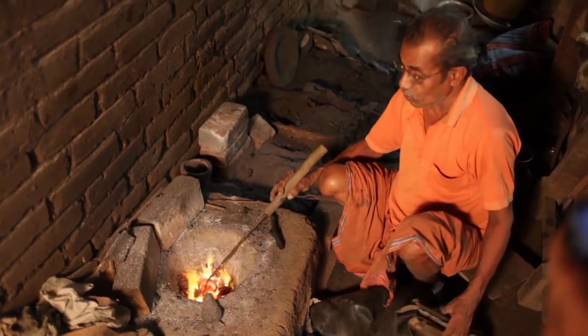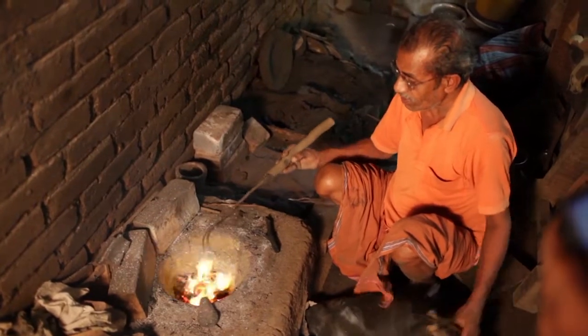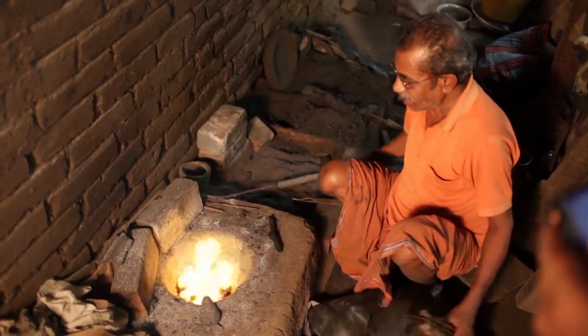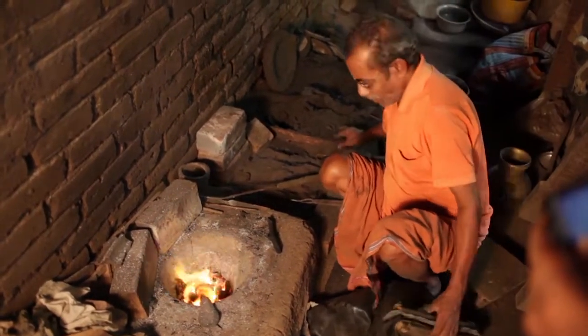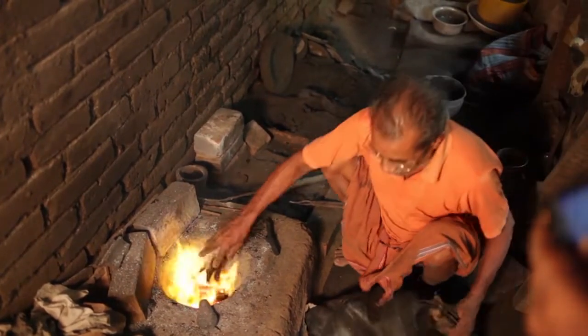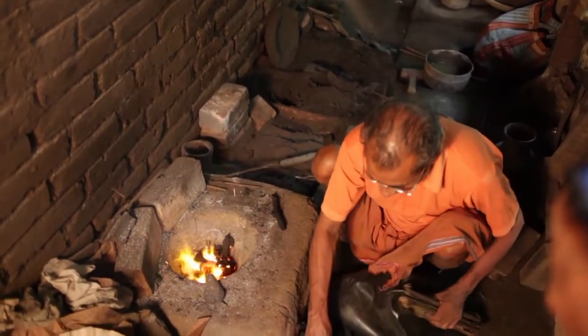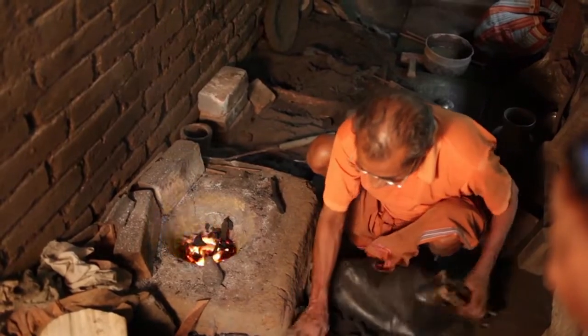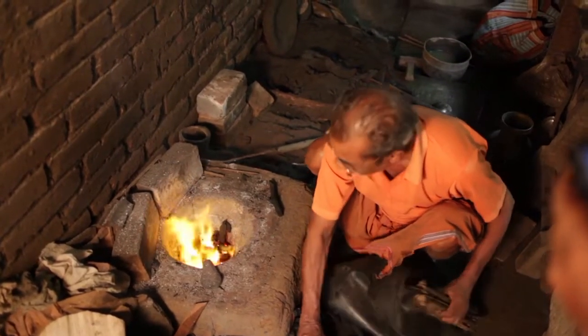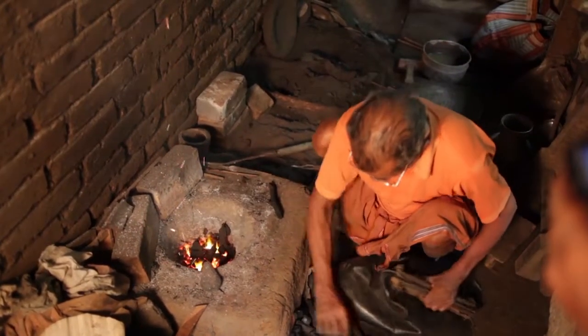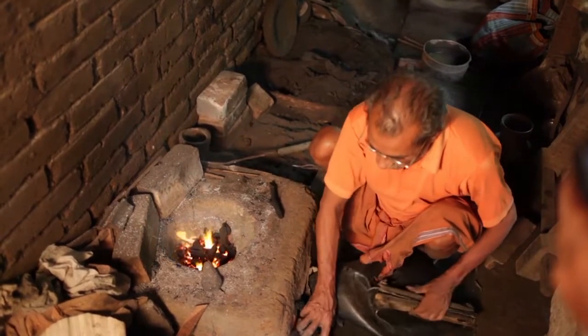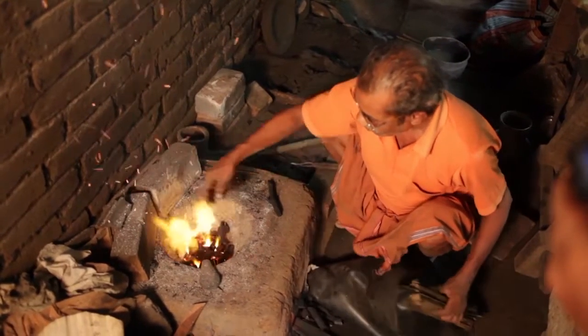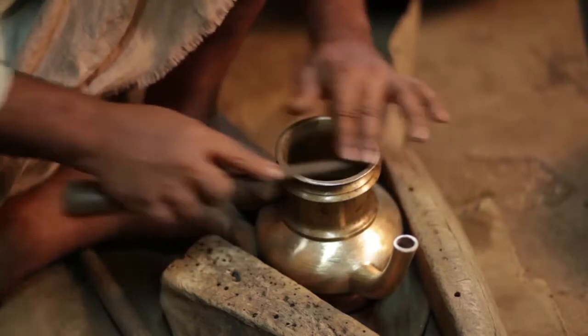Bell metal is generally the terminology used to refer to an alloy of a proportion used to cast bells of about 20 to 25% tin with copper, with about 10% lead added to make the alloy more castable. But since unleaded bronze with a high tin content is very brittle, it was not used very widely. This is known as Vengalam.